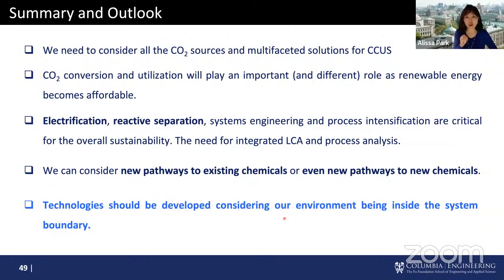So if we can somehow target only, for example, in terms of carbamate, if we can only transfer energy to the carbamate site and release that CO2, it could be a minimum energy requirement because you don't need to heat up the entire reactor, the entire system, to get to 120, 140 degrees C. Chemical engineers are very used to isothermal operation of reactors, right? Isothermal reactor here and reactor here. So we capture CO2 at either ambient temperature or 40 to 60 degrees C. And we increase the entire reactor system to 120, 140 degrees C to release. But if we can do really targeted energy transfer, it could be the minimum energy penalty.